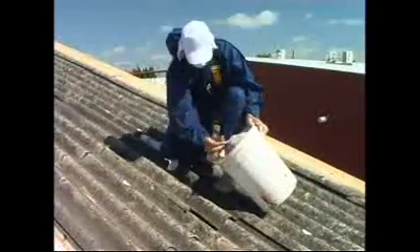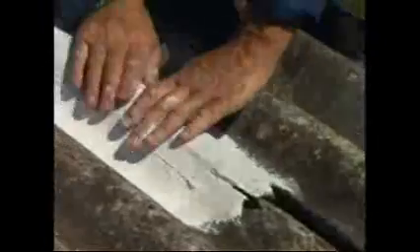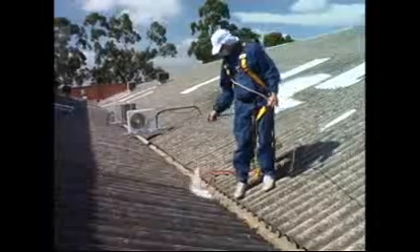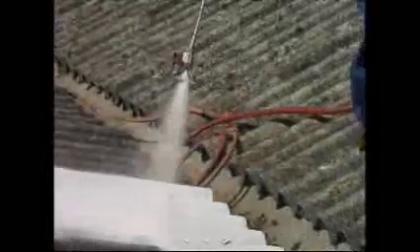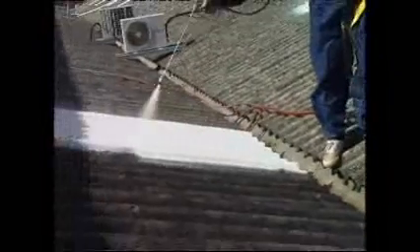After the roof has been primed, apply Fibroseal Top Coat to cracked areas. While this is still wet, embed 100mm wide reinforcing fabric, or scrim, over the crack and overcoat with Fibroseal Top Coat, and wet out the reinforcing fabric thoroughly. Then allow to dry. The Fibroseal Top Coat may be applied by airless spray, or small areas by brush or roller, to a wet film thickness of approximately 300 microns. Special attention should be made to achieve complete coverage of the raised surfaces of lichen.